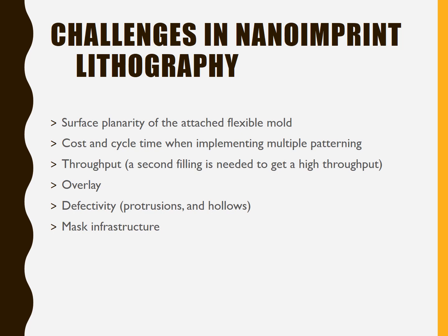This costs more time and more money, but it's still lower than other lithography techniques. Then we have overlay and defectivity, though we can avoid the stitching errors that other lithography techniques produce. We do have some protrusions and hollows created by nanoimprint lithography. This is minimal, but it does happen. And the last challenge is mask infrastructure.